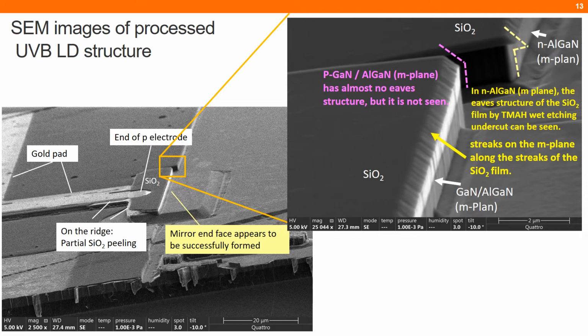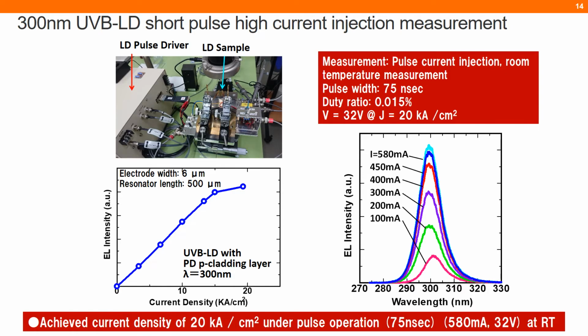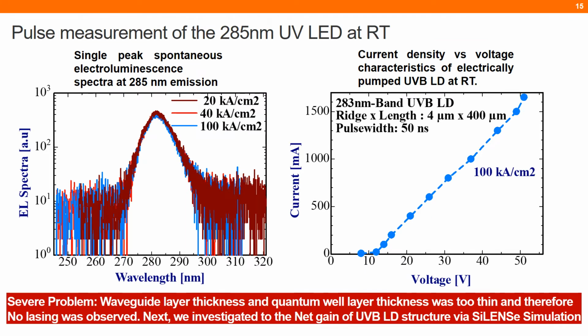And we processed the laser structure. This structure was around 300. This one was a relatively smaller wavelength of 285, and again we could get a very high current density of 100 kiloamps per centimeter square. In this case, we used a ridge width and length of the laser diode of about 4 micron and 400 micron. Here the pulse width was 50 nanosecond.